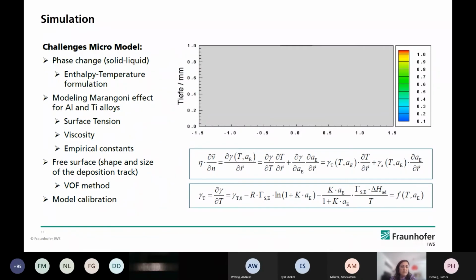So I'm not an expert on simulation. We have fortunately the support there of the colleagues working with Andreas, but there are some challenges, as you may know, while working with these simulation processes and also from the process side, which are listed here: to follow the phase change, to model the Marangoni effect, which is well known for LMD processes, and especially challenging for aluminum, concerning the evaporation side effects of some elements that take part there.